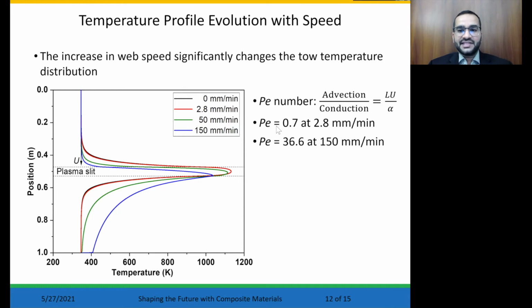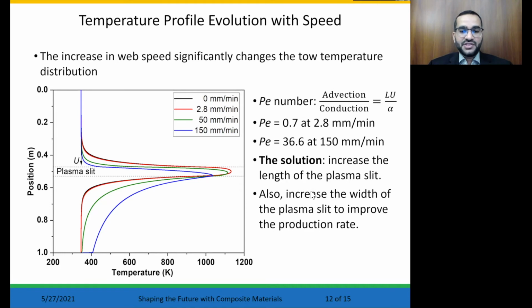Péclet number indicates the ratio of heat transferred by advection and conduction processes. At higher web speed, Péclet number is large, which suggests higher heat transfer by advection. Therefore, vertical graphene deposition on carbon fiber is limited to lower web speeds at which the residence time is long and the temperature is high.